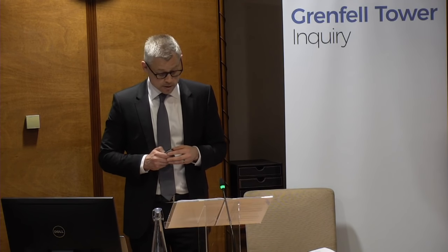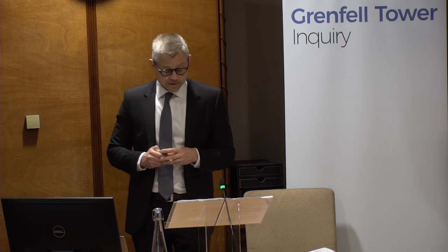The rate of flame spread is dependent on the heat transferred to the material and the material's thermal inertia. This is because the rate of flame spread is governed by the rate at which the material adjacent to the burning region can be heated to its pyrolysis temperature. Upward flame spread is generally faster than downward flame spread. This is because in upward flame spread, the flames and hot gases, which rise due to the effect of buoyancy, as I've already mentioned, will preheat the material ahead of the advancing flames. This preheating does not occur in downward flame spread, which is therefore slower.